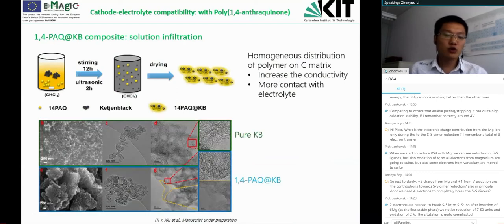So here I show you some typical electron microscopy images, and basically the first column is the pure carbon matrix, while the second column is the carbon with the active material loading. So we see the amorphous region, which was marked by these orange colors. They are dispersed well on the carbon matrix.